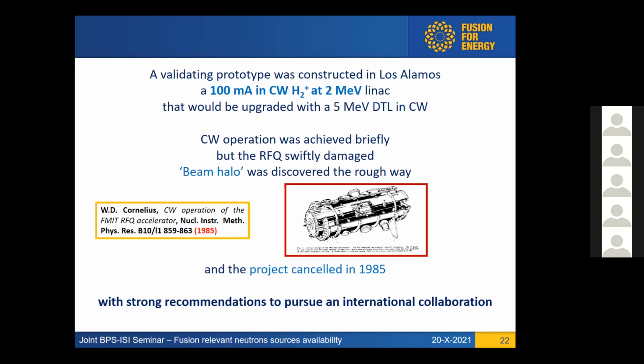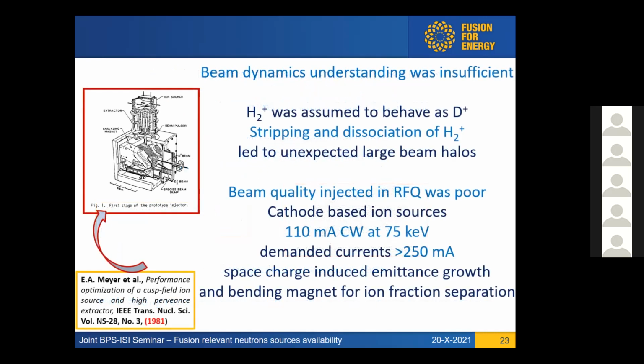And when you have very high current, this beam halo, if you increase the duty cycle, then it starts to make noise, because then the power starts to be substantial. The energy deposited starts to be substantial. So they tried to run 100 milliamps in CW with an H2+ at 2 mega electron volt, which is very low energy also. And basically they didn't manage. They managed to run for a few minutes and they burned the RFQ in a very rough manner. So basically the project was stopped in '85. They canceled the project because they saw that the technology was not ready.